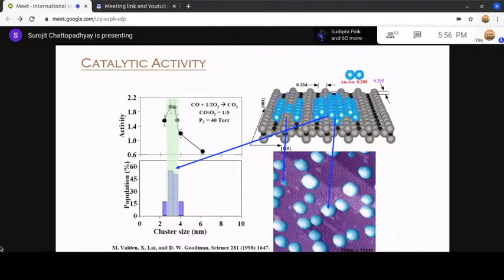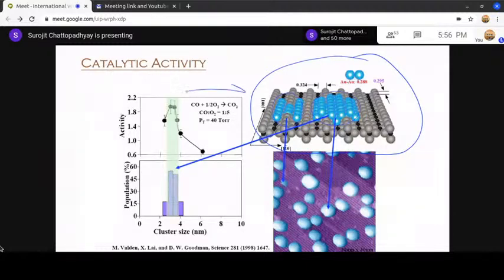Nano gold, if you have a particular kind of gold, which is only possible if you deposit gold on a crystal of titania, TiO2, can convert this CO into CO2, which is bad but not deadly. So you can have this reaction going, CO plus half O2 giving CO2. So basically you are oxidizing carbon monoxide to carbon dioxide. Normally carbon monoxide is very unstable. If it finds an oxygen, it will react.